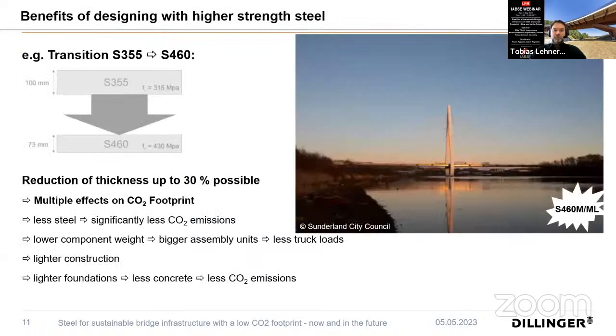So what would be benefits of using higher strength steel? This is just an example, a very easy example. If you calculate from S355 to an S460, in an ideal case, a thickness reduction of up to 30% is possible. This is an ideal case, but in reality, usually you also end up with 15% or up to 20%, which you can save. And this, of course, has multiple effects on the CO2 footprint.